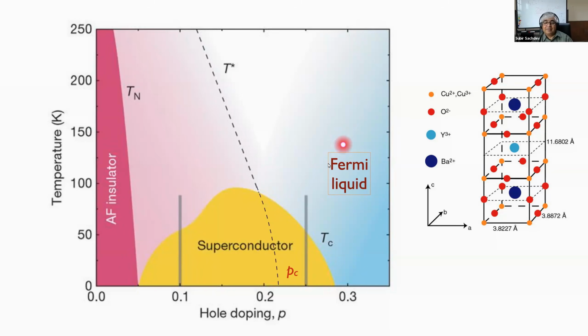One is the conventional Fermi liquid, where basically if you start from free electrons and do perturbation theory, you will get the correct answer of many details of the electron spectrum. Then there's sometimes called the pseudogap metal, which is a metallic phase in the sense that transport looks metallic, but with a much lower density of carriers than a Fermi liquid. And so there's complicated issues on something called the Luttinger theorem, which tells you that, in fact, the size of the Fermi surface should be the same as in the free electron gas. That's a crucial theorem of condensed matter physics, and that seems to be violated in this metal.